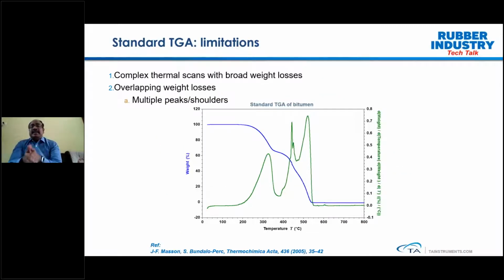Now, let's talk about the limitations of standard TGA, and then we can talk about the advanced mode, which can be a solution for dealing with this kind of complicated situation. Many times, if you look at the standard TGA, you may see a complex thermal scan with broad weight losses, like what you see here. And many times you see overlapping weight losses with multiple peaks and shoulders. Here the sample is showing a multiple decomposition pattern, and it is also overlapping.